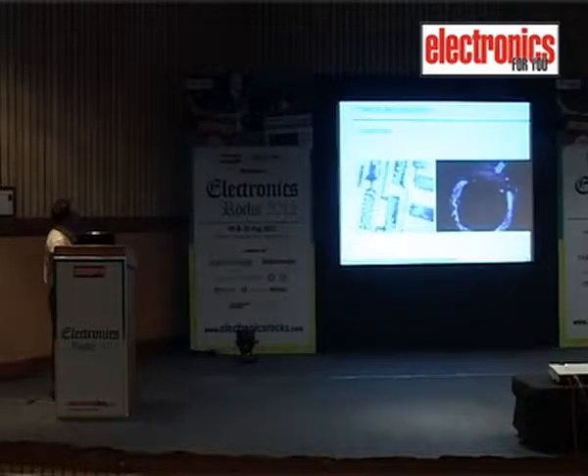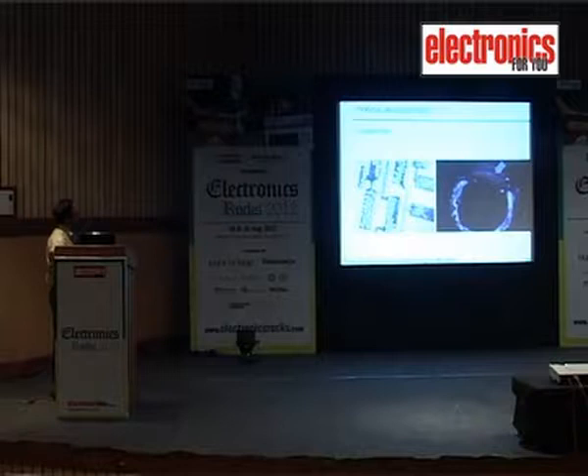Similarly, the de-wetting, you can see some traces of solder it has taken, but it is not taking fully. This is mainly due to intermetallic growth between the copper and the solder. If bare PCBs are stored for a long time, such effects can be seen, and to take care of this, what we are doing right now is